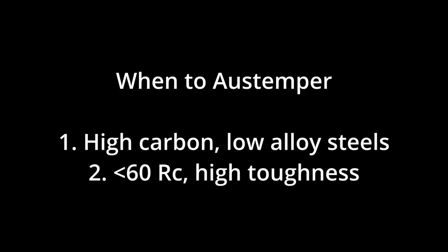Even 52100 does not benefit as much from Austempering. But if you want something in the lower hardness range of like 55 to 59 Rockwell or so, you can have more toughness for a given hardness, even in something like 52100. If you're shooting for 60 plus Rockwell, especially 62 or higher, quench and tempering is probably the way to go, and you can improve your chances by controlling your austenitizing temperature or just selecting a steel which is easier to control the carbon in solution.